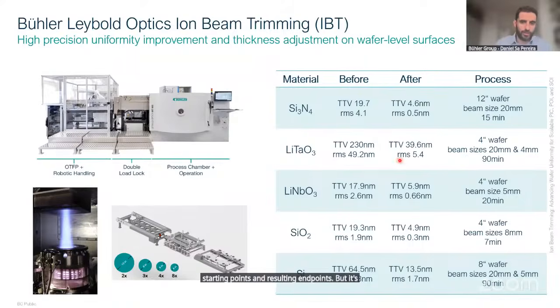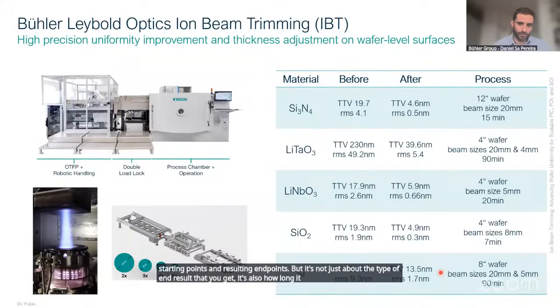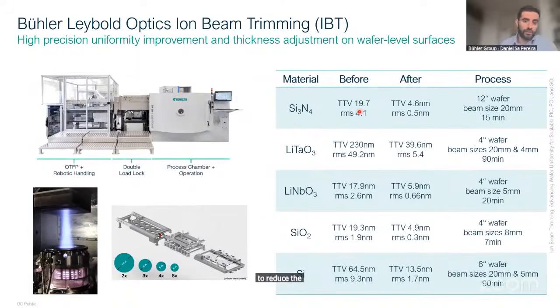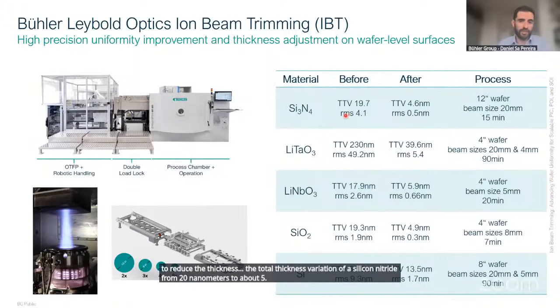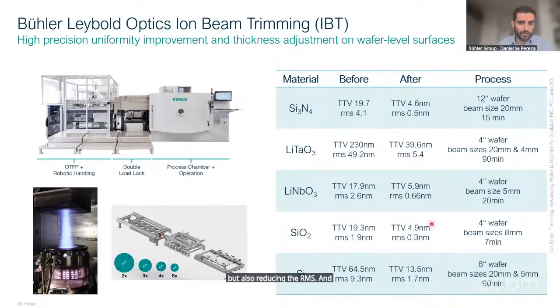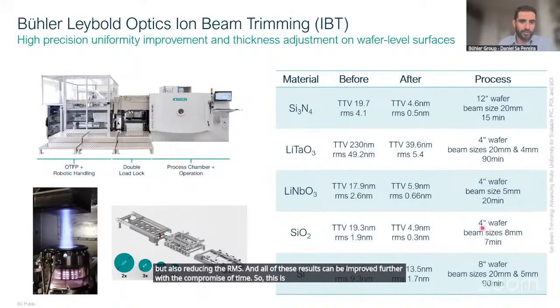But it's not just about the type of end result you get, it's also how long it takes you to get to such results. So for example, you see here highlighted 300 millimeter wafers and a 15-minute process to reduce the total thickness variation of silicon nitride from 20 nanometers to about 5, but also reducing the RMS. And all of these results can be improved further with the compromise of time. So this is basically just an example of how ion beam trimming can be beneficial for multiple platforms.